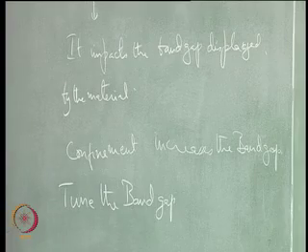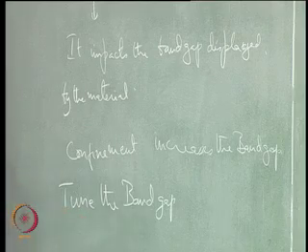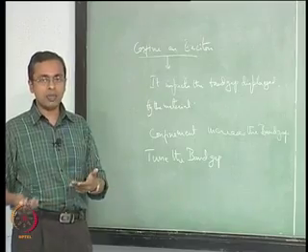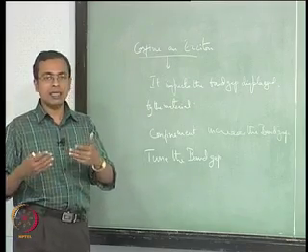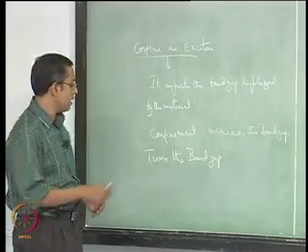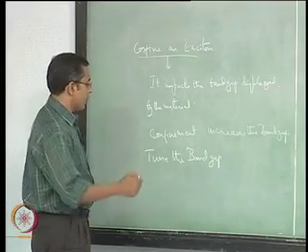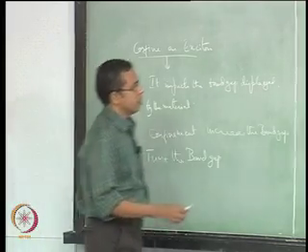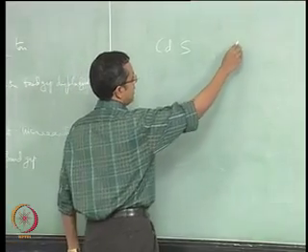So confinement increases the band gap, and by using the impact of this nanoscale structure, you can tune the band gap and get materials with the band gap that you desire, and therefore you can use it with several advantages associated with the fact that the chemical composition is the same. And so that is a big advantage. For example, some of the materials that people work on are materials such as cadmium sulfide and lead sulfide.